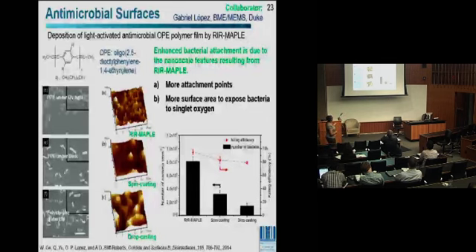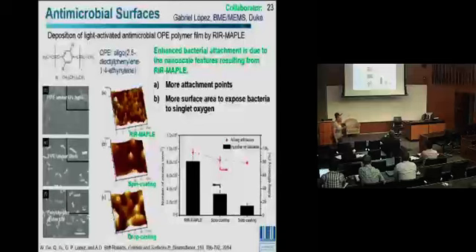This demonstrates that when we deposited this OPE by MAPLE and shined a light, we do actually kill bacteria. The thing that was really interesting, though, is that the RIR-MAPLE films have this nanostructure to the surface roughness. If you look at the surface roughness for MAPLE, spin coating, and drop casting, you have this very high nanoscale surface roughness, which led to a much larger attachment of bacteria on the surface compared to the other two approaches, and along with it, a higher killing efficiency. So this nanoscale surface roughness, which is unique to the MAPLE deposition process and how it works, is part of the challenge we're facing with the organic solar cells. While it's a challenge for the solar cells, it's an advantage for this application.